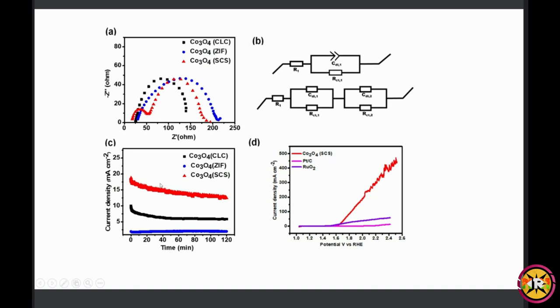Now for the stability study, I have done chronoamperometry, and up to 2 hours my catalyst is stable in the same reaction conditions. And in figure D, we can see one is platinum on carbon and one is ruthenium oxide. Basically these two are the benchmark catalysts reported over the last decade as good catalysts for OER. When I have compared my data with the benchmark catalyst, it is far better. So from figure D, we can conclude that Co3O4 SCS is showing better OER activity than the benchmark catalyst.